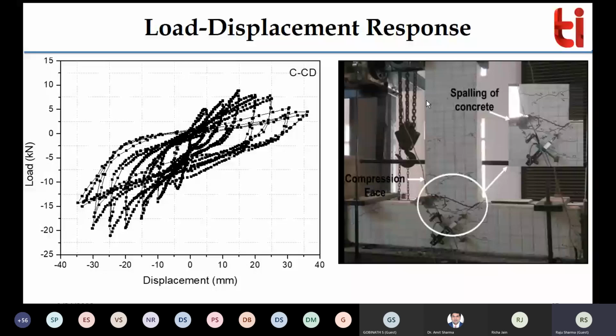So after that testing we got this kind of hysteresis of that beam column joint, and you can see lots of cracking on one face, because that face is not designed as a tension face. In the traditional way we have designed one as compression, one as tension. So the tension face performed well, but on the compression face tension occurred because of the cyclic loading and it may fail, right? And lots of cracks you can see on the joint also, right? Because of that you can see the hysteresis performance on the left side of this beam column joint.